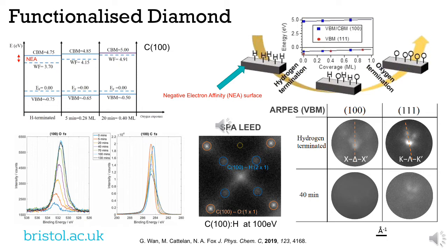Towards realizing a solid-state long-life radiovoltaic diamond battery, my group has been studying the properties of graphene Schottky contacts on functionalized semiconducting diamond. Our measurements of the Schottky barrier height for graphene on hydrogen terminated diamond suggest that a carbon-14 diamond battery should be capable of harvesting the energy of beta decay not only by conventional beta voltaic operation, but